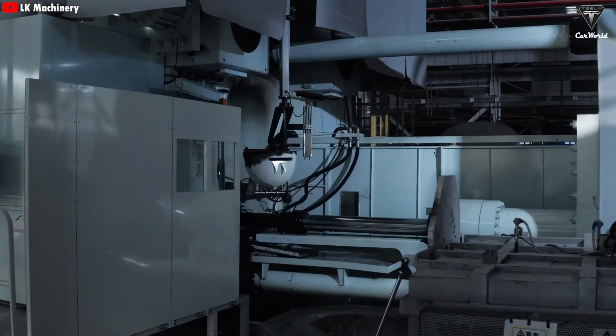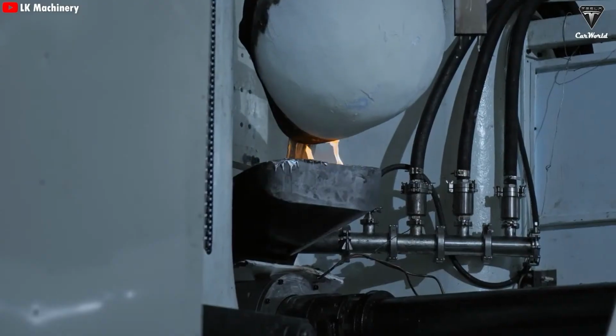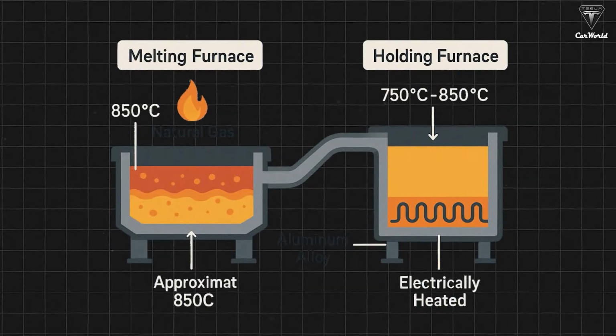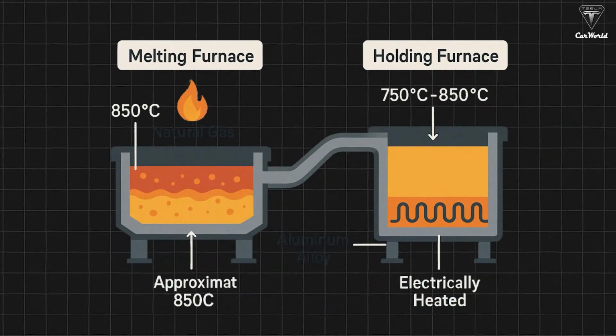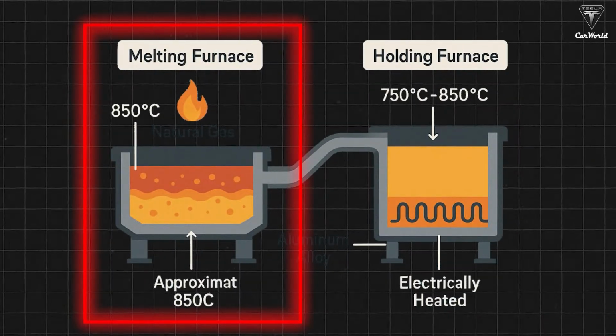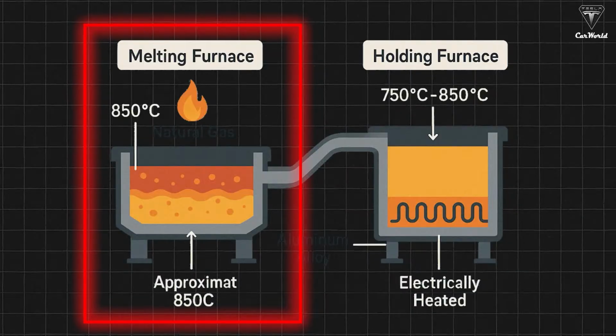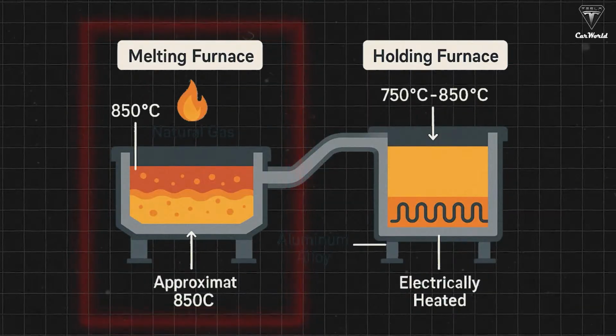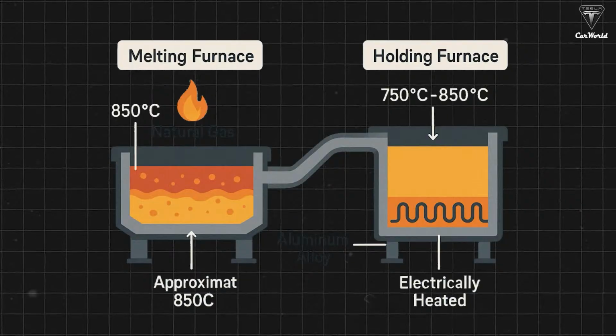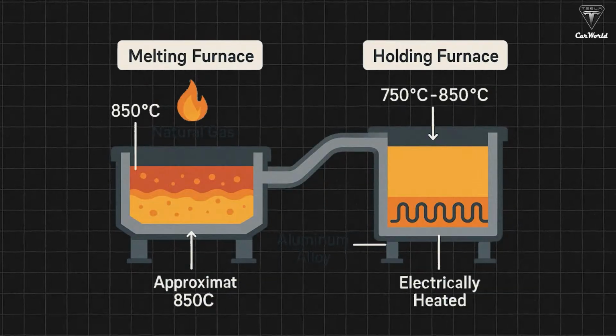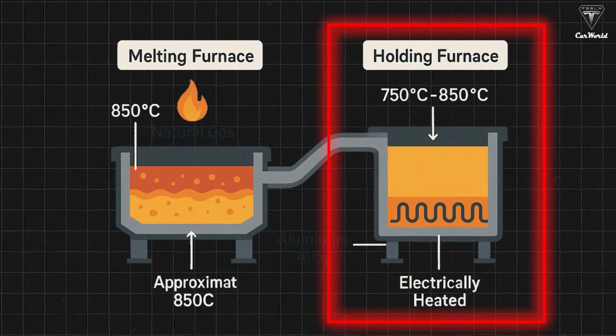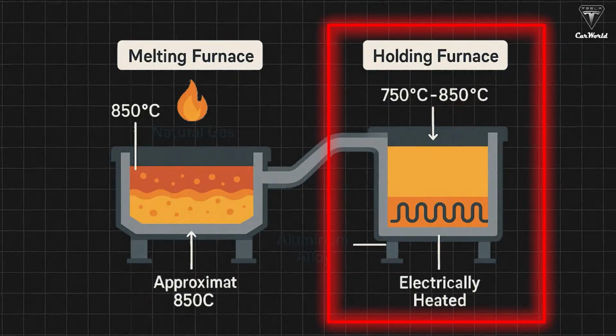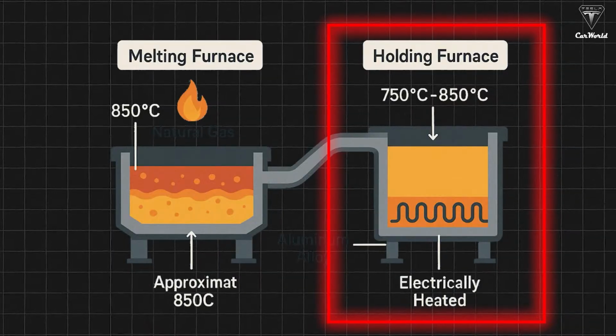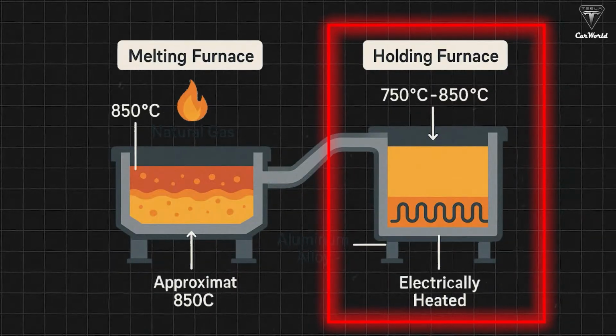First, the process still begins with preparing the materials. Tesla will melt down new aluminum ingots along with leftover aluminum from previous castings in a furnace heated to around 850 degrees Celsius. Then, any surface impurities are removed before the molten metal is transferred via heated pipelines to another sealed furnace, which maintains a temperature between 750 degrees Celsius and 850 degrees Celsius.